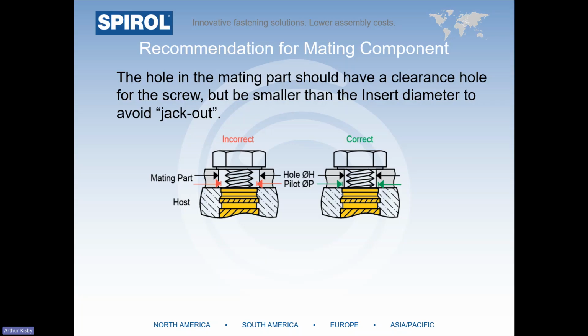The mating part can also significantly reduce resistance to rotational torque when it doesn't support the top bearing surface of the insert. We call this condition jackout. When the hole of the mating component is larger than the face of the insert, there is nothing to prevent the insert from dislodging and moving up into the void of the mating part. To avoid jackout, we recommend that the mating component's hole is smaller than the face of the insert, but large enough to allow the bolt to pass through.